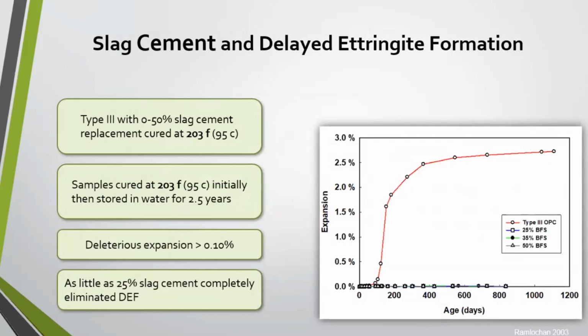This test was specifically designed to address delayed ettringite formation. In this case, a type 3 cement was used with differing replacements of slag from 25% to 50%. It was cured at 203 degrees Fahrenheit initially, and then stored in water for 2.5 years. Deleterious expansion for this is defined as 0.1%. You can see the ordinary Portland cement curve there, and then everything else, 25% through 50%. DEF was basically eliminated through the use of slag cement here. So that's pretty powerful evidence.